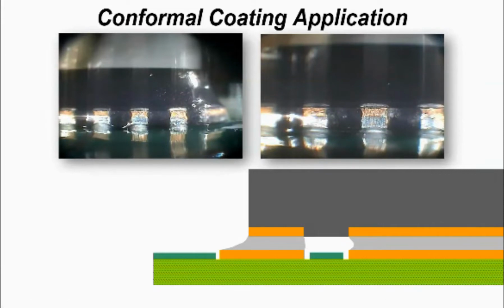If we talk about conformal coating, one of the other things which is not talked about a lot, but has been seen in a couple of technical papers, is making sure you match the thermal performance of the materials when you're doing temperature cycling. We know that with BGA, if you get a lot of conformal coating, particularly an epoxy resin, underneath the BGA and temperature cycle it, you will stretch joints, you will deform joints and possibly break them.